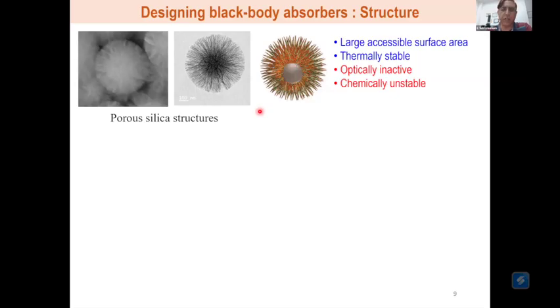We started with these structures, which we form in our lab, that are completely made of silica. The reason this structure was appealing to us is that you have these beautiful structures when you see them through an electron microscope. You have these fibrous structures. It almost looks like a sea urchin with a lot of tiny spikes pointing from a central core. The morphological aspect was interesting for us, which means that it can have a large accessible surface area.